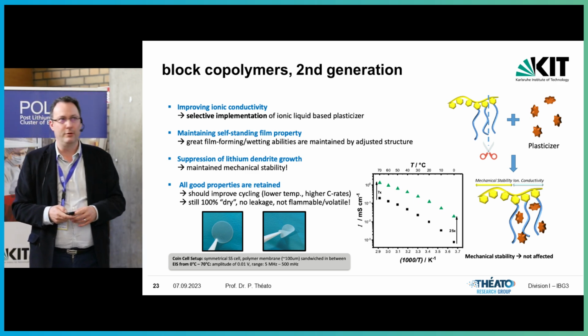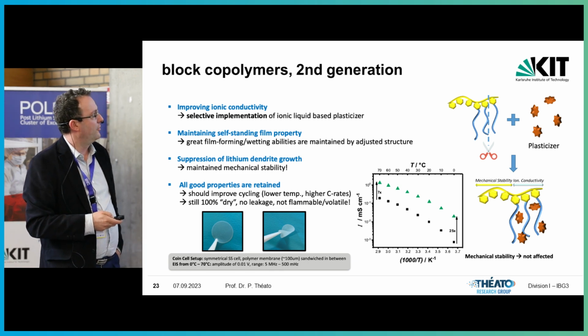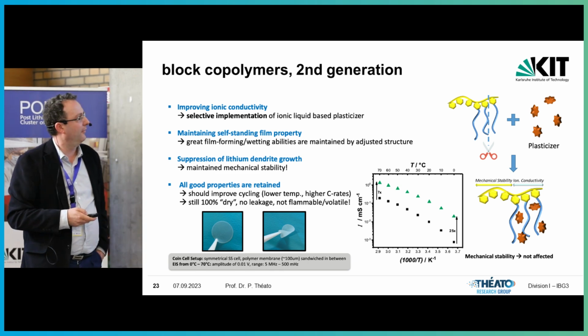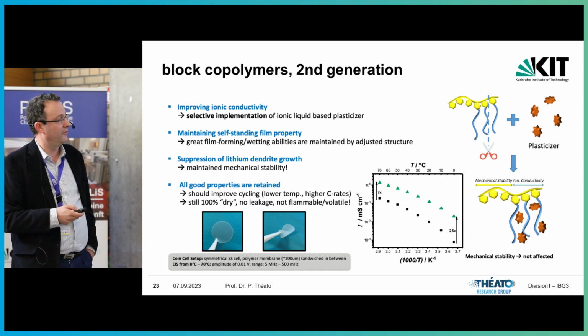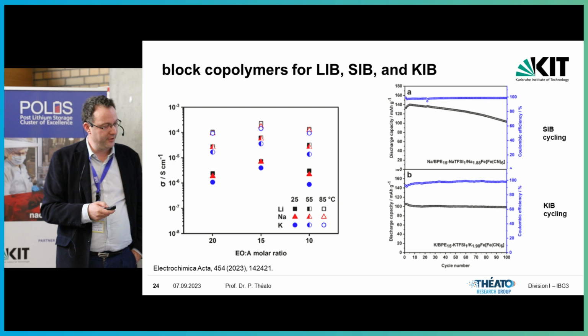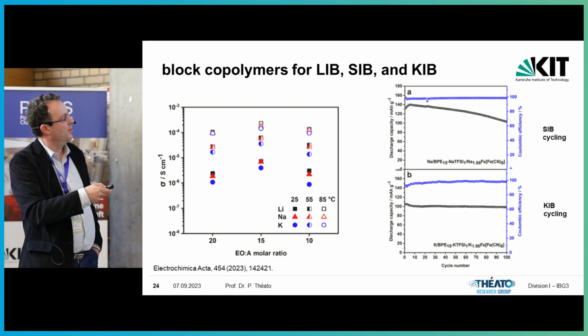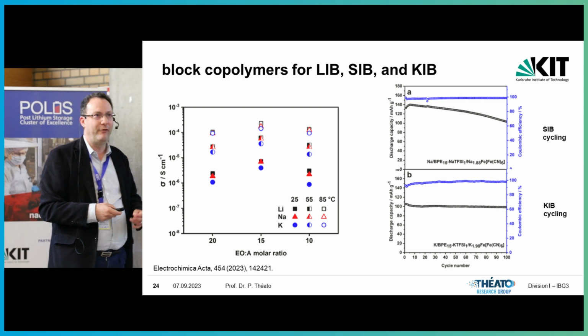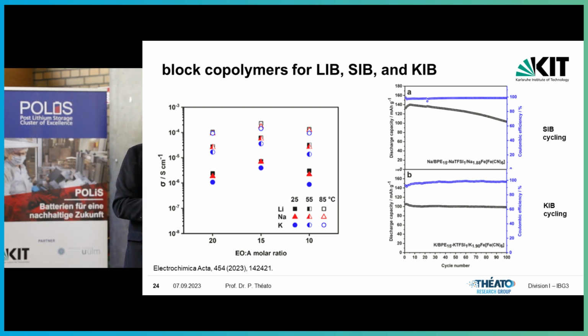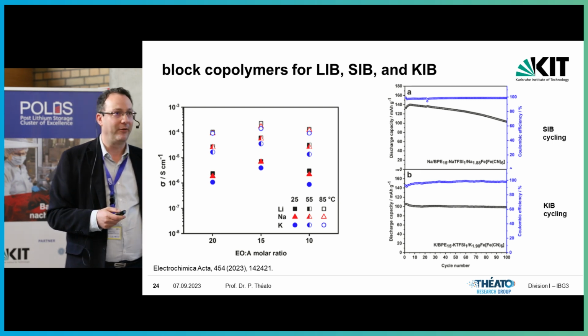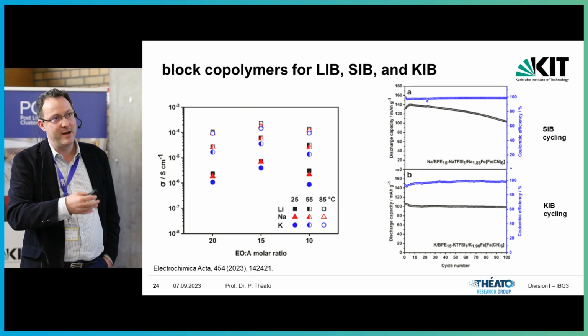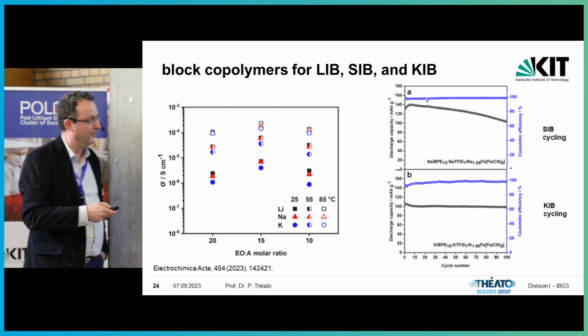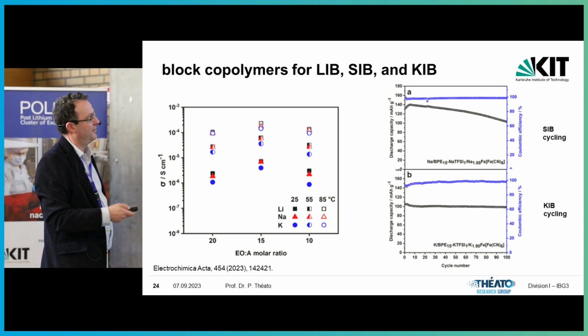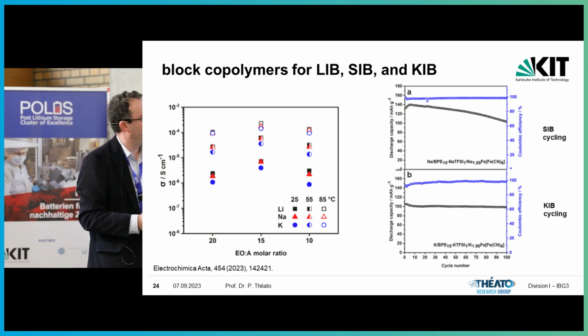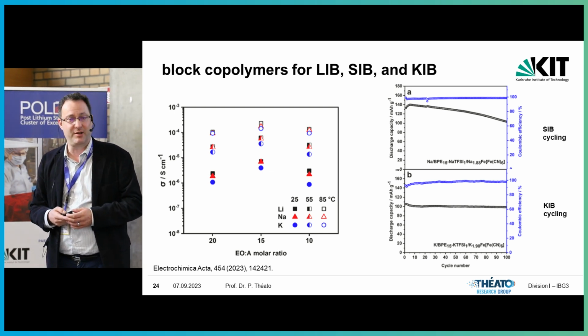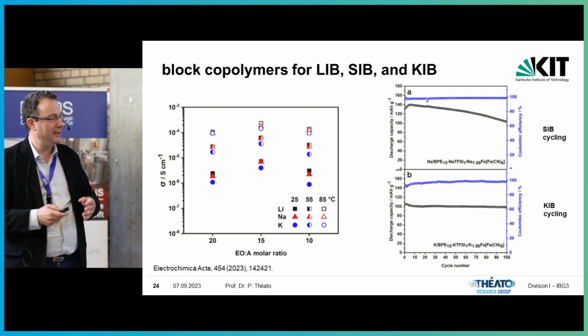And the chairman is getting nervous, and you're probably getting hungry. So just one last thing, and I'm happy that Fabian is in the room, because we collaborated and we used the same polymer for different ion conductivities, not only for lithium, but also for sodium and potassium. The interesting thing is they don't really differ much. We don't understand why, but that's what it is. Fabian and his group members can make rather stable cells out of this as well, here for potassium and for sodium cycling. So I think it's a rather promising polymer system, being maybe slightly universal in a way.